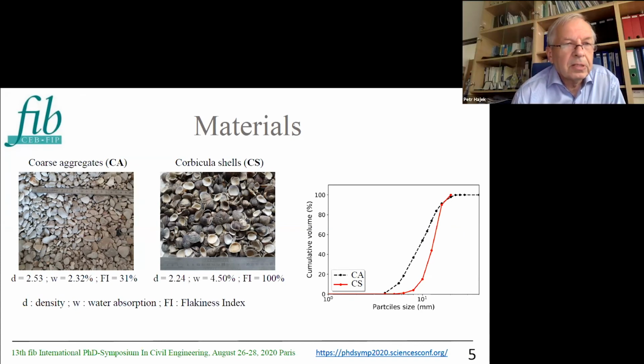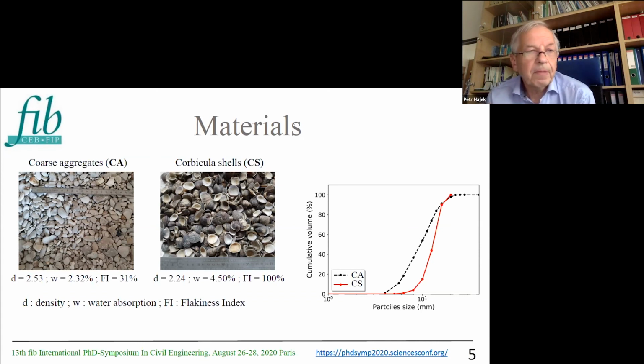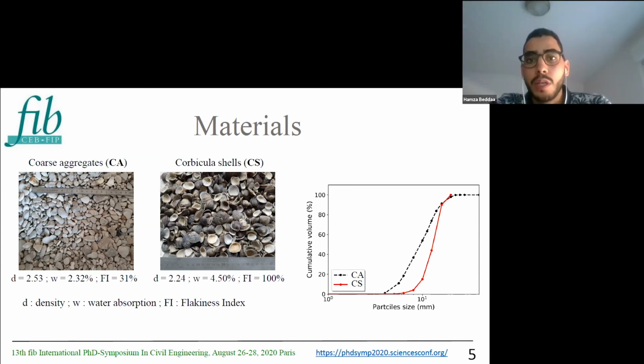What about the durability properties of the concrete made with shells, especially freezing and thawing resistance? Thank you for sharing your amazing work. The question is by Cassiani Daniel. The durability tests for this concrete are carbonation and chloride diffusion. For these two properties, there is no effect up to 20% of substitution, but we didn't test 100% substitution. The other durability properties are not tested.